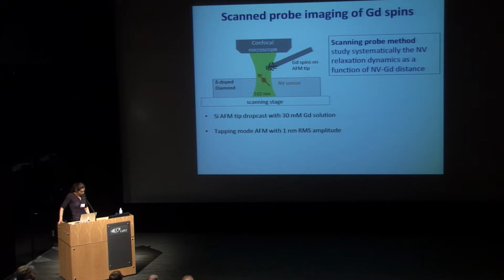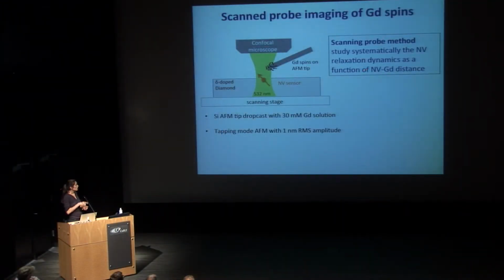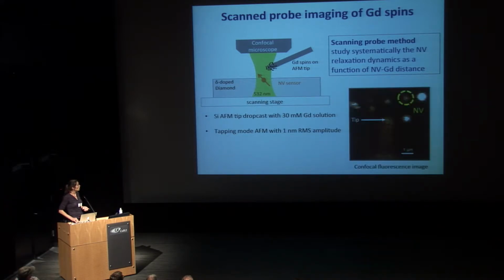So as I said, we want to get to the point where we can do scan-probe imaging and scan some protein or other structure over an NV center. And so we wanted to study systematically the NV relaxation dynamics as a function of this NV to gadolinium distance. So we took an AFM tip, a silicon AFM tip, functionalized it with 30 millimolar gadolinium, and scanned it over an NV center with about a 1 nanometer tapping amplitude.